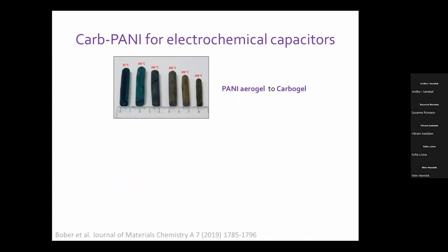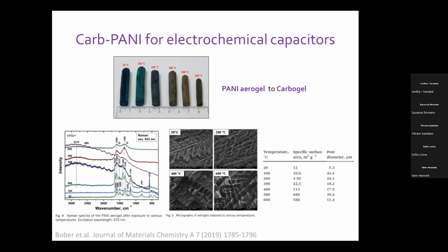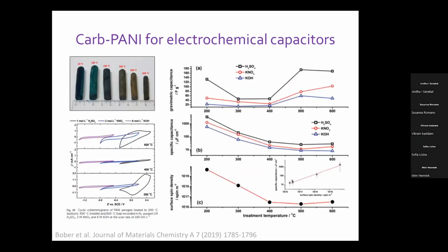Okay, so one more example from collaboration with our colleagues from Czech Republic, Patrycja Bober, is this wonderful example of PANI aerogel carbonization to carbogel. So these materials are really astonishing because they're super light, mostly consisting of air, which also makes them very difficult to measure electrochemical properties. But not only that, the morphology is preserved, and the shape of this PANI aerogel during carbonization, there is only some shrinkage of material, but you also see that during the carbonization, specific surface is being developed, pore diameter changes, so we get a really nice material which can be used for electrochemical applications, in particular as electrode material for electrochemical capacitors. But the question is how it actually works.